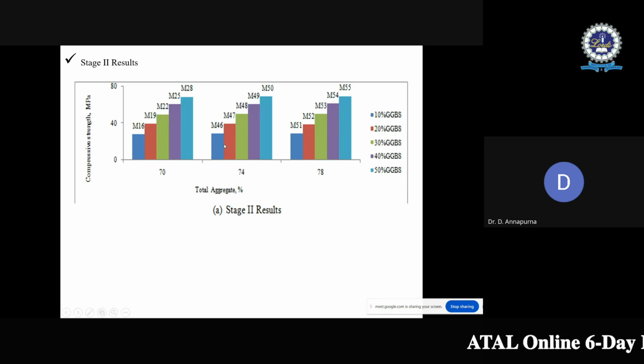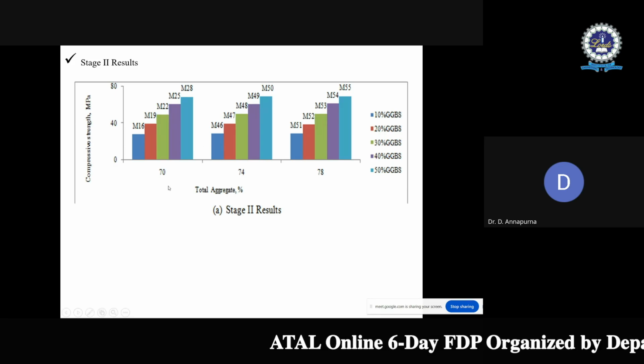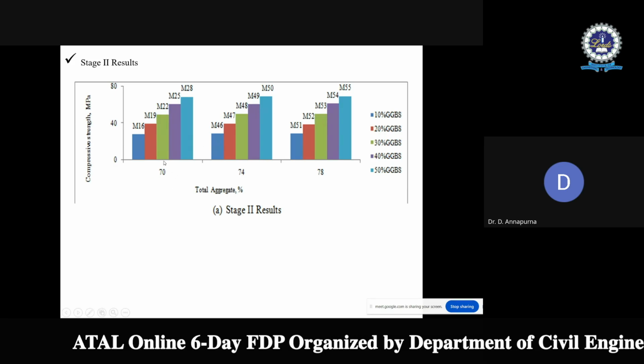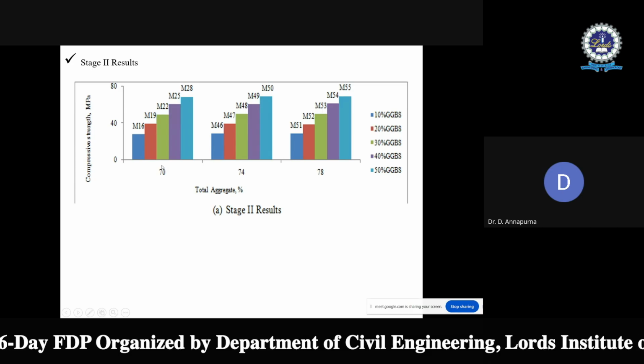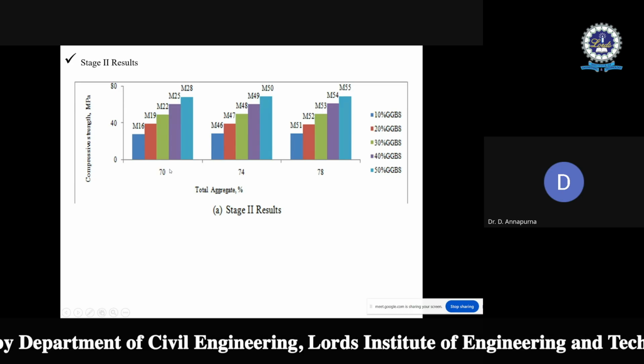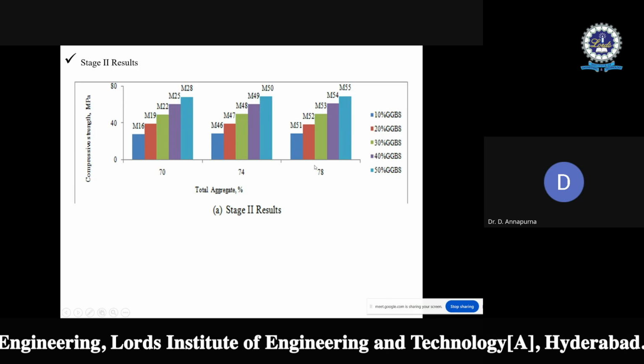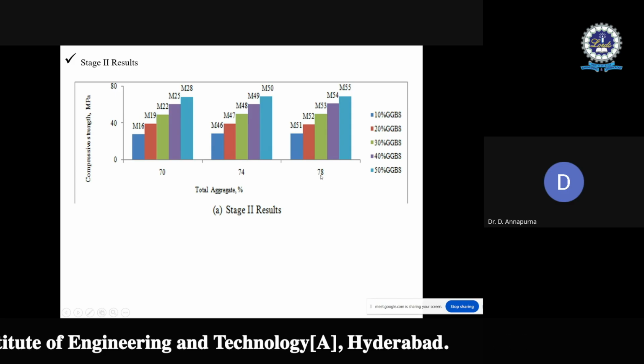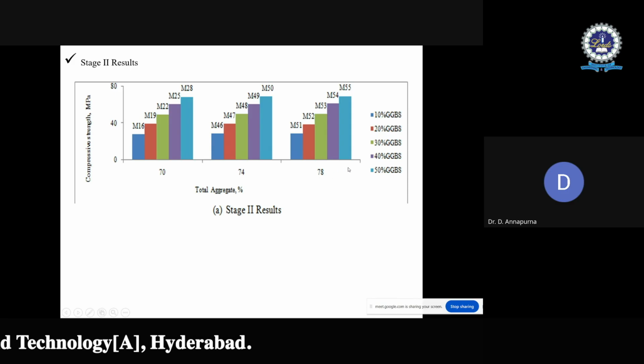So that is the reason for the next stage of work, 70% total aggregate is maintained, because when we check with respect to 70% and 78%, the 78% mix will consist of only 24% of alkaline liquid and fly ash.